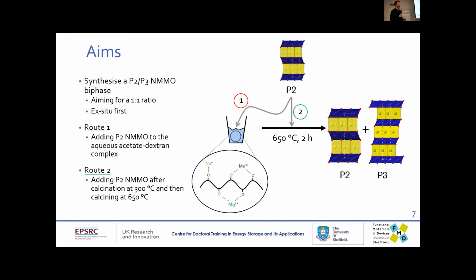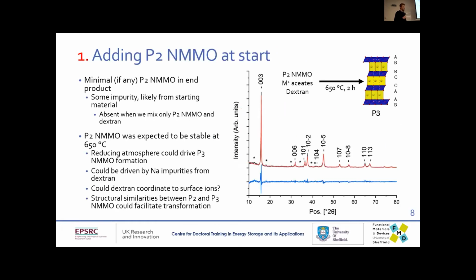So route 1 is to add it to this aqueous solution, dry that down, calcine it, and try and get P2 and P3. The second one is to start with the acetate dextran solution, dry it, calcine it in this pre-calcination step at 300 degrees, and then mix the P2 powder into it, and then calcine at 650 degrees. And then I will get onto a slightly different route after I explain what happened here. So route 1, I get almost entirely P3. There are some small impurities, but I don't think they're the original P2 that I started with.